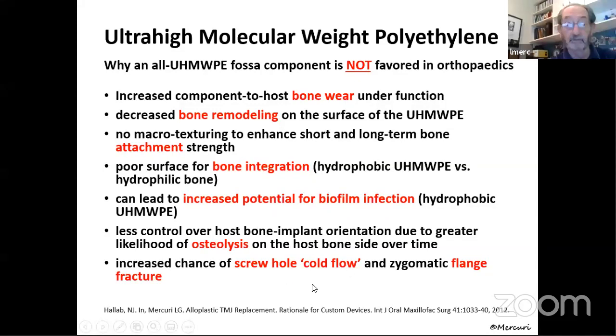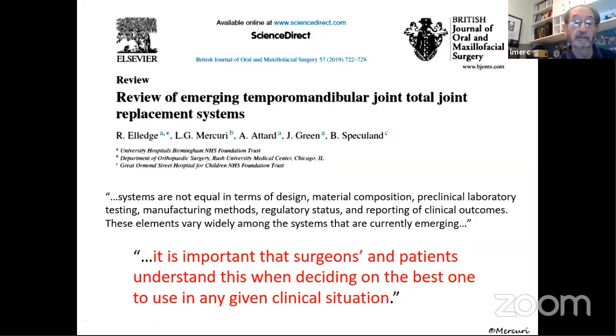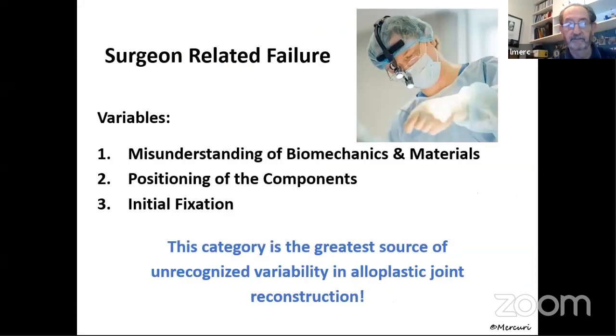And the other issue with ultra-high molecular weight polyethylene is that if you put screws through it, as I'll show you in a clinical case here in a couple minutes, you're going to get cold flow. And if that device is not solid against the bone, the screws going through that device are going to fail. So what did we learn from that big study that we did of emerging devices? We learned that it's important for surgeons and patients to understand what's going on with these devices and why a titanium wrought device is better than a cast device.